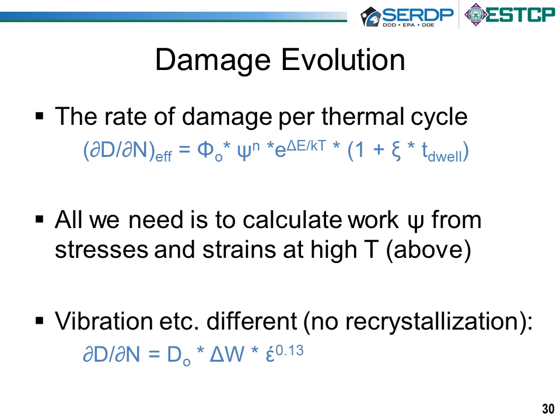Now, in vibration or anything else where the temperature is constant, the situation is different. In that case, we don't get the recrystallization that you saw, and what you get instead is cracking just through the grains. And in that case, the damage function is a lot simpler. Even if it's after some aging and the precipitates have changed and so on, the properties are different, but you just calculate the work in the cycle.